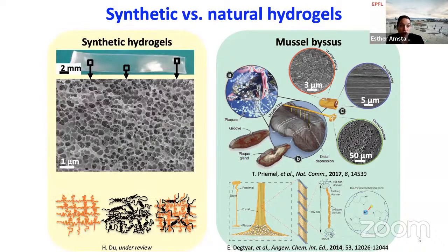Whereas if you look at hydrogels, the way that we synthesize them, while we can tune the composition with very high precision, we can to a certain extent control structure, but only over very limited length scales. But if you then look at the composition and structure as a function of the location, you realize that most of them are homogeneous and they have some sort of an ill-defined structure. Okay. Now, that is a bit of a shame, I think. And the question is, why can't we do better in terms of controlling local composition and structure?